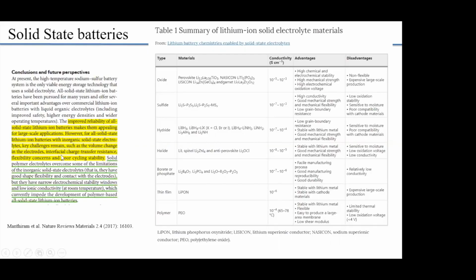He wrote a paper about solid state batteries, and this is what he comments: The improved reliability of all solid state lithium ion batteries makes them appealing for large scale applications. However, for all solid state lithium ion batteries with inorganic solid state electrolytes, key challenges remain, such as the volume change in the electrodes, interfacial charge transfer resistance, flexibility concerns, and poor cycling stability. Solid polymer electrolytes overcome some of the limitations of the inorganic solid electrolytes. That is, they have good flexibility and contact with the electrodes, but they have narrow electrochemical stability windows and low ionic conductivity at room temperature, which currently impede the development of polymer-based batteries.